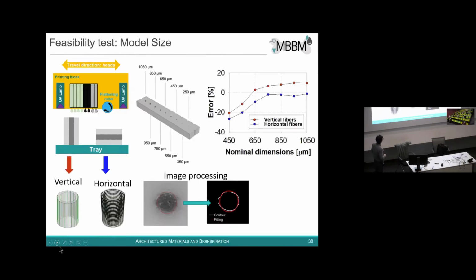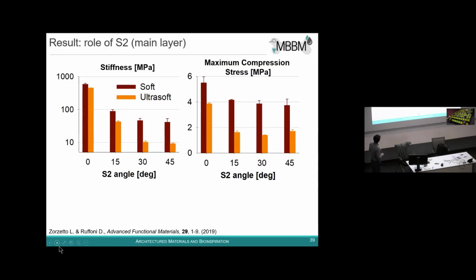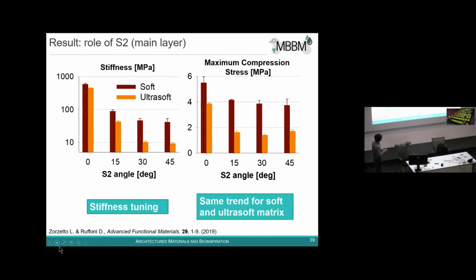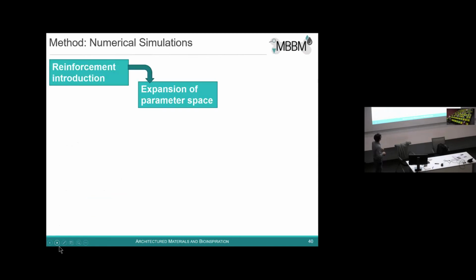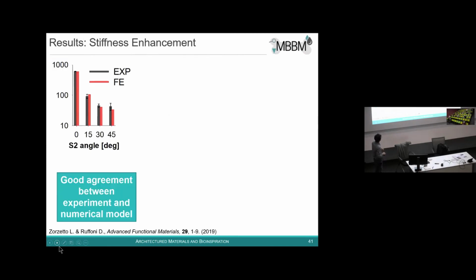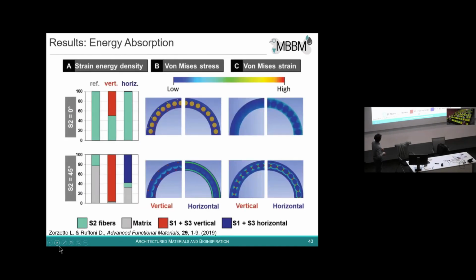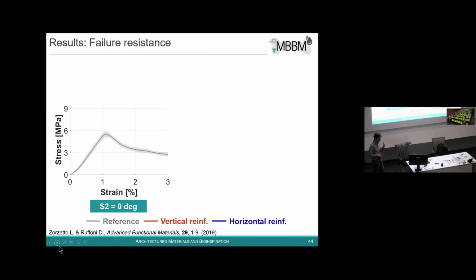And then what we did, we first did a little bit of an analysis of the apparent stiffness of the system by changing the fiber winding angle, and also the maximum compressive strength. So we see that this technique allows us to tune or program the stiffness of the system. And we also had a similar trend, qualitatively speaking, for soft and ultra soft matrix. Maybe I will quickly skip this because I want to show you this, which is most interesting. Then I come back to this.